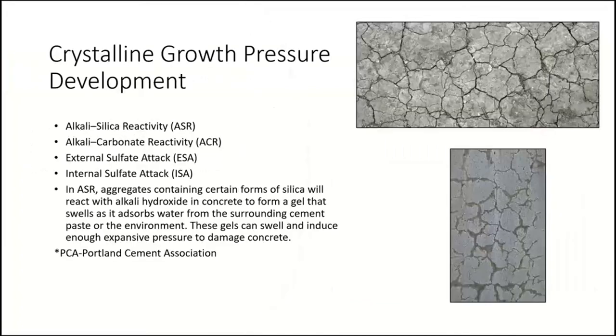The other thing that we don't talk about as much, because typically on the front end, if you're looking at concrete mix design, you want to see if you have reactive aggregates. Sometimes they slip in, most commonly alkali silica reactivity or alkali carbonate reactivity, and you'll have this crystalline growth pressure developing. You need moisture for that to happen. Chlorides and de-icing chemicals make it worse, and it's hard to stop something like ASR in a bridge deck. Overlay treatments will slow it down. There are other things you can do to slow it down, but I don't know that you can stop it. So hopefully you do your work up front, and make sure we don't have reactive aggregates in our mix. That's critical.